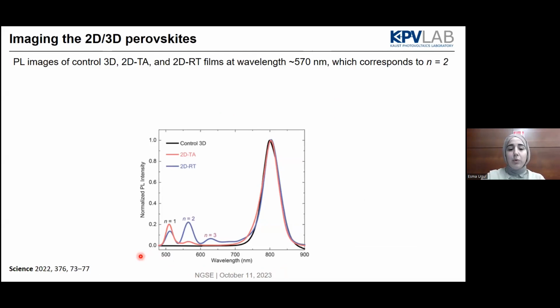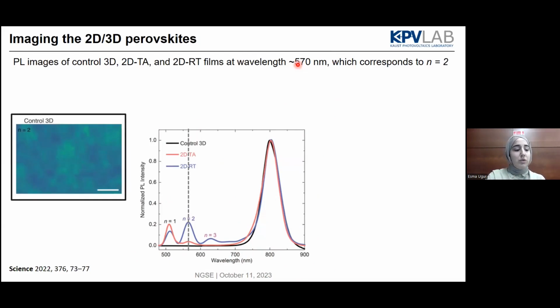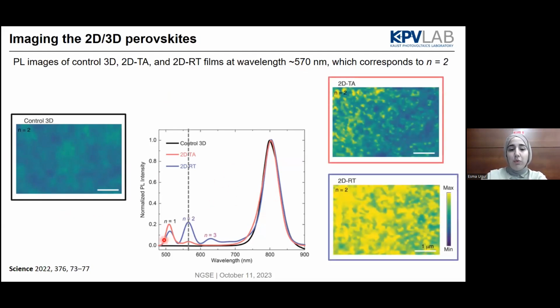So in general, when you have a PL, you have the main peak of the 3D perovskite, and you have your passivation peaks. So for instance, when you get this plot, you may not know if you really have a uniform formation of the 2D on the surface or not. So how we can see it, I can show you as an example for n equals 2, around 570 nanometers, you can get the image using the hyperspectral microscope. You can get the image for the control. So yeah, we don't have any formation of the 2D. You don't see any excitonic emission here. But for the other samples, for instance here, you see the formation of these 2D, which is not that super uniform here.